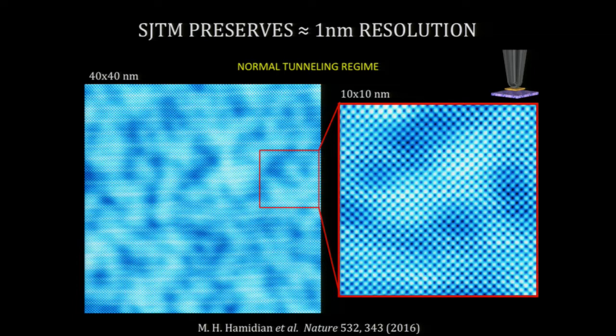So here's a topograph taken with our superconducting tip. And you're like, that's great. It looks like you have atomic resolution. Well, keep in mind our tip is probably about a nanometer big. What you're really seeing is that the tip has a crystal on it, and has an atomic lattice. And then here's your sample. As you raster your tip across your sample, there's going to be highs and lows between the 2. That's why you see what looks to be an atomic corrugation. We can tell it's about a nanometer resolution because if you look at the variations, and we know that this is there in the cuprates, these dark and bright spots are about a nanometer big. So we think the resolution of the tip is on the order of a nanometer in this case.